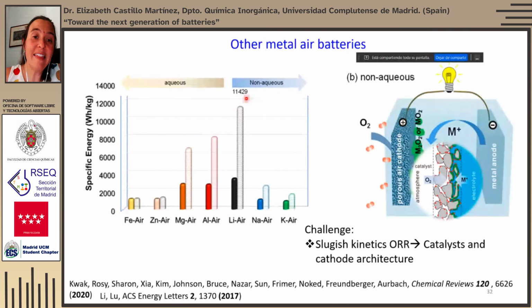If we were to compare the lithium-air batteries with other metal-air batteries, we see that in principle, the specific energy for a lithium-air battery based only on the weight of lithium and oxygen is much higher than for any other chemistry. But if we calculate the specific energy based on the weight of the discharge products, this lithium peroxide or sodium peroxide, then differences are not that large. And especially if we take into account that aluminum and magnesium, although they are thermodynamically unstable in water, can form some passivation layer that allows them to operate.